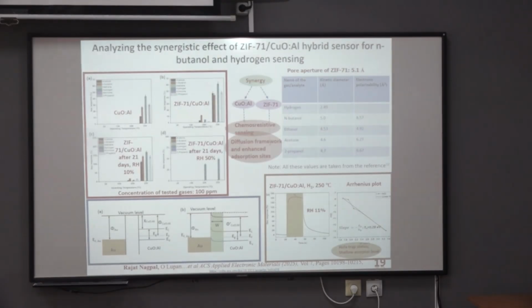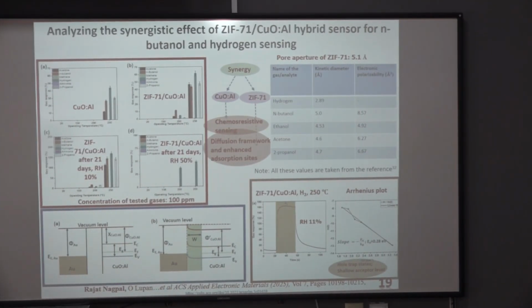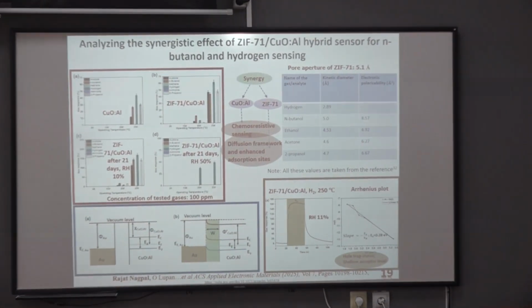If we look at one example in the dynamic sensing curves, for example this one, in recovery time, generally scientifically we take 90% recovered as the recovery time. We do not have to wait for 100%, but there could be a drift, higher than the baseline. It could be due to the presence of defect states, so we could interplay with defects to improve recovery time. But here we can see it is almost recovered within less than 50 seconds. Yeah, but you are not going back to the previous state, because you have to wait a little bit longer. Yeah.